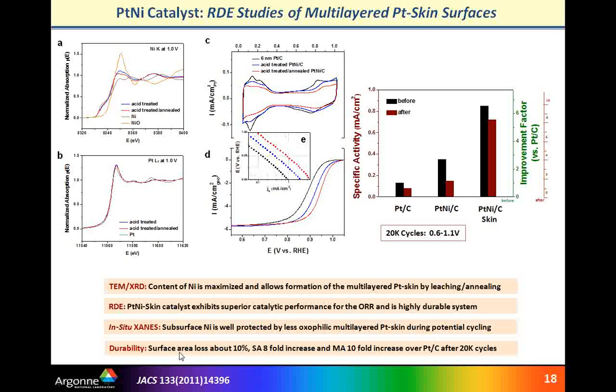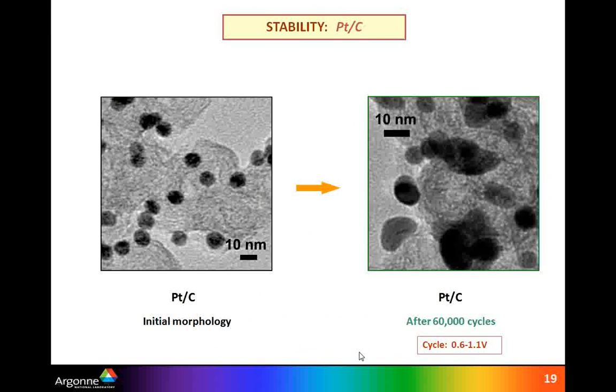So, total surface area loss was somewhere around 10%. And if one compared that to state-of-the-art platinum carbon catalyst, that goes up to 40%. So the final properties are 8-fold increase in specific activity and almost 10-fold increase in mass activity over platinum carbon catalyst. So not only can we tackle issue of stability with bimetallic systems, but also our goal was to explore what is going on with multimetallics.